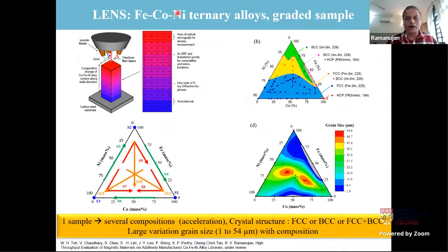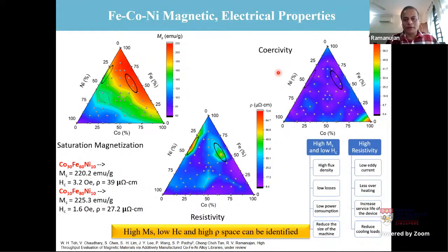So we've prepared this for the case of iron, cobalt, nickel, which, as you all know, is a very attractive system for finding new materials because it combines all the 3 ferromagnetic elements. So we prepared graded compositions and used rapid X-ray technology to find out what the crystal structure is. We could also rapidly find out the grain size, which is related to the magnetic properties, the electrical properties and the mechanical properties. Then we determined the magnetic properties and the electrical properties for this entire ternary space of iron, cobalt, nickel. So we could map the MS, saturation magnetization, the coercivity, and also the electrical resistivity.